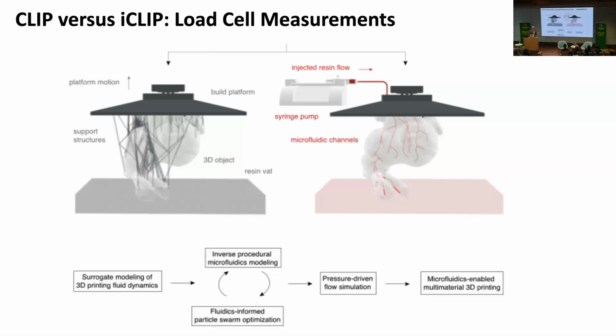And what's also interesting is normally when you print, you have to have a lot of supports on a part to hold it onto the platform. Well, when you're pushing resin through and you're innervating the part with these channels, those forces go away. And now we've designed all the software where the software decides where the channel should be to minimize the forces. And then when we don't need the channel anymore, we close it with light. So we basically start pushing the liquid into different regions. And so now we can start printing things without supports, which minimizes waste, and it goes faster.